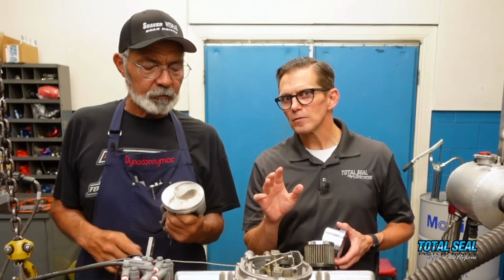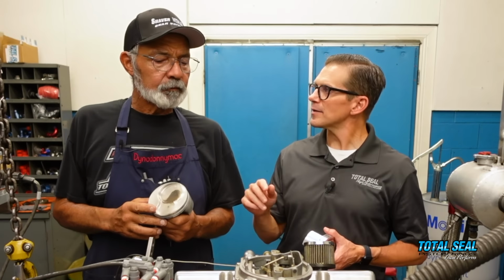A few years ago, the guys at Engine Masters did a dyno test similar to what we're gonna do today and show you the results on. They ran a 5/64th ring versus a 1.2 millimeter ring. So that's basically going from a 2 millimeter ring to a 1.2 millimeter ring. And they saw about a 7-8 horsepower advantage going thinner like that.